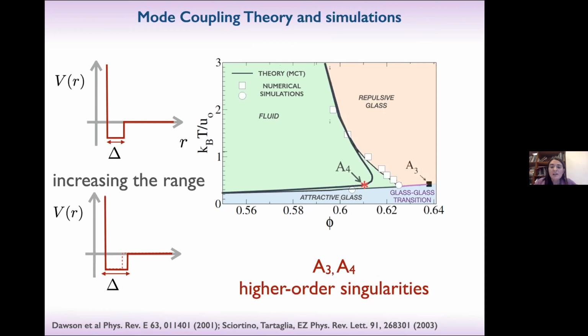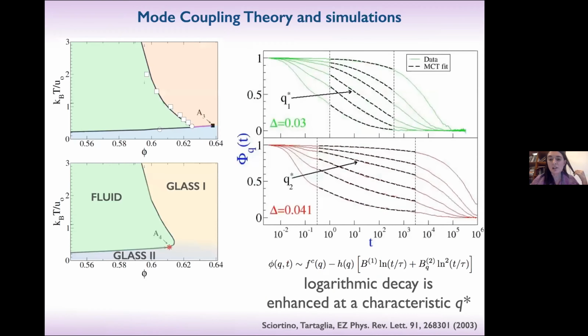And so we then decided to learn from the theory and to slightly increase the range of the square well. And we worked at the particular delta for which this glass-glass transition line would shrink and merge the two glasses, and so this A4 singularity. And then we performed simulation at a given state point in the vicinity of the A4 singularity, so always in equilibrium, and we monitored the behavior of the density correlators.